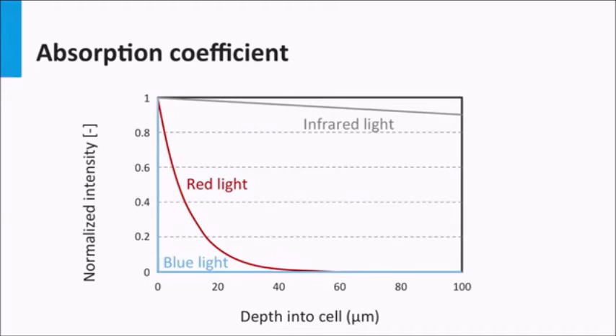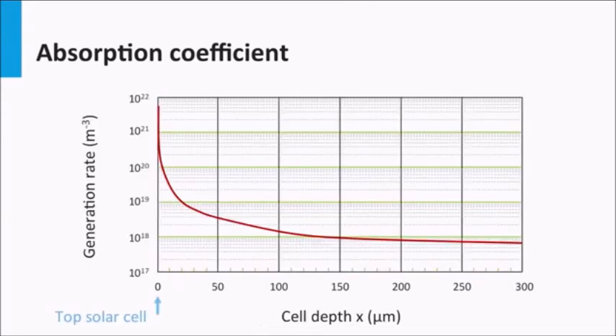Let's take as an example the normalized light intensity with position in the silicon bulk. As you can see in this graph, the blue light is already fully absorbed within a few nanometers. The red light requires an absorption path length of 60 microns to be fully absorbed. The infrared light is hardly absorbed, and after an optical path length of 100 microns, only 10% of the light intensity is absorbed.